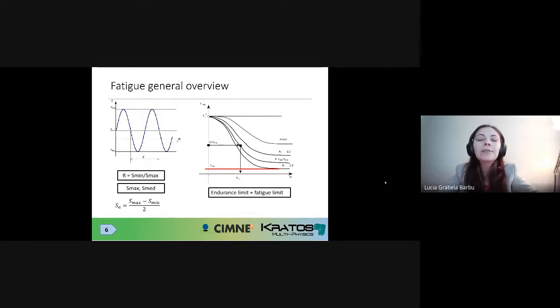And this is a limit that's very important for the industry, specifically when they design for high cycle fatigue loading. Because if you manage to maintain the stress state inside the specific component that you are developing below this endurance limit, then you have no fatigue behavior. You will have no alteration of material properties as you apply the cyclic loading. This is a very easy way to design, I would say. And this is basically the main design practice in the past 20 years or so. However,